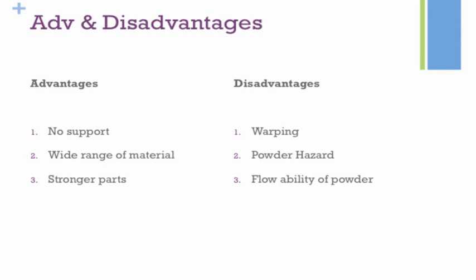Another disadvantage is the flowability of powder. This is fairly generic to all powder bed fusion technologies, because the powder needs to flow well as you roll it across the surface of the build platform. If your powder particles are not circular, there's a chance they might not flow well, the powder distribution on the build plate will not be uniform with varying thickness, and your laser may have a difficult time melting the cross-section.